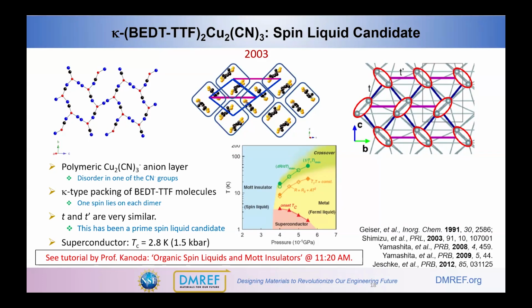In this realm, ET does play a role. For many years, this has been a prime candidate for a spin liquid, a copper cyanide material, which also has a kappa type packing, but it was recognized by Noda and others that the spins here are located essentially on a triangle that could form a spin liquid type phase. This material has a copper 1 cyanide anionic layer. There is disorder in one of the cyanide groups. This material does become a superconductor under slight pressure of 1.5 kilobar. Again, I refer you, I'm not going to go into so much detail, but there's a talk here at 11:20 that will go into this in much more detail. Hopefully this will just entice you about what was happening here.